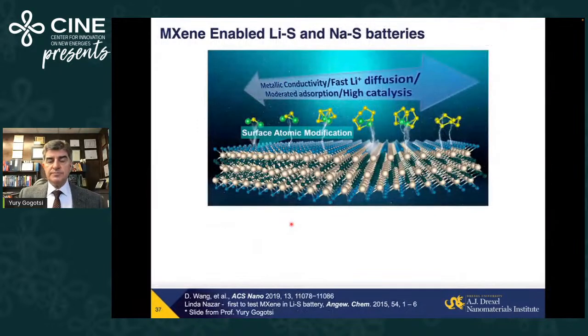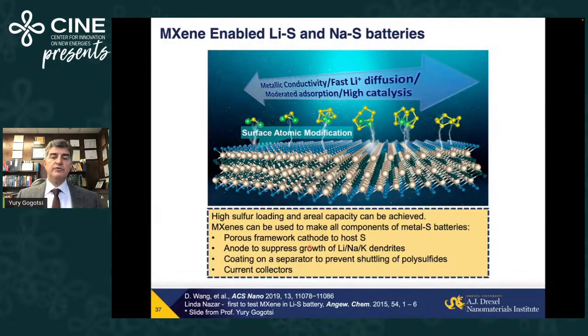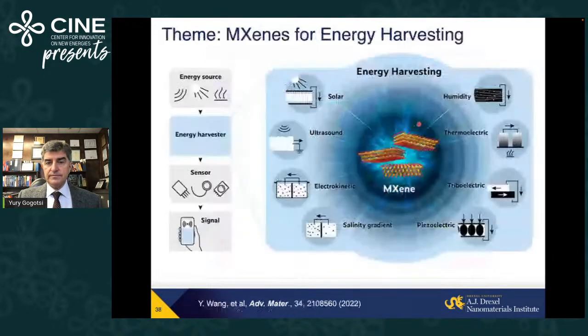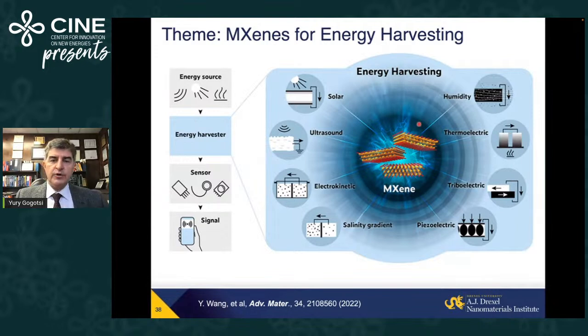There are other applications being explored, for example, lithium sulfur, sodium sulfur, potassium sulfur batteries. It's in addition to suppressing dendrite growth on the anode side. MXenes are conducting, they compensate for low conductivity of sulfur, they can absorb polysulfides, prevent their transport through the separator, and also catalytically decompose those. There are applications also beyond energy storage, and I think I'm already running out of time, so I should finish.